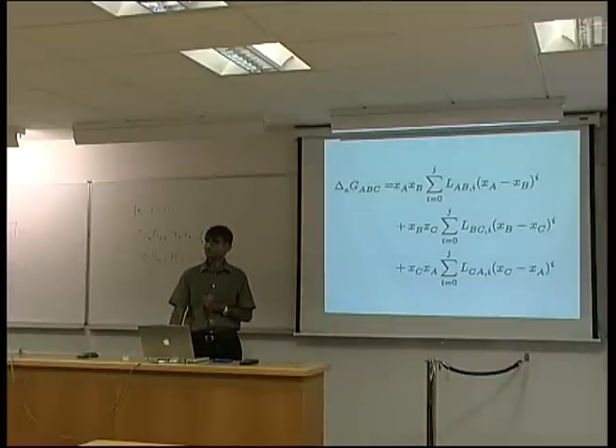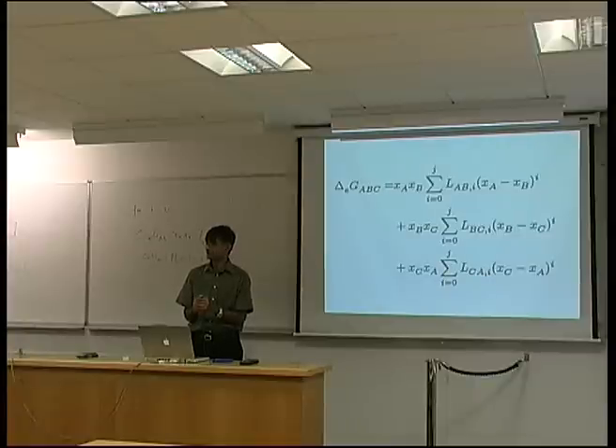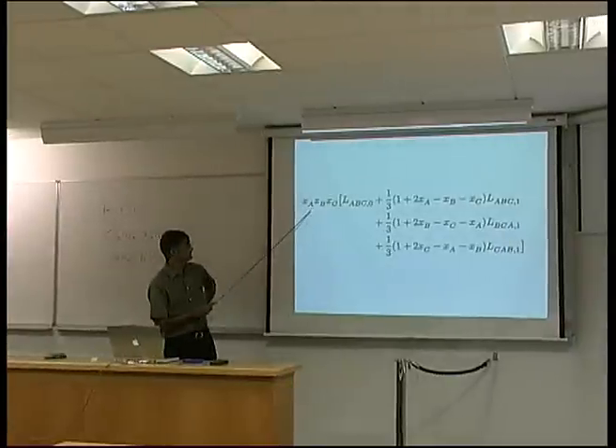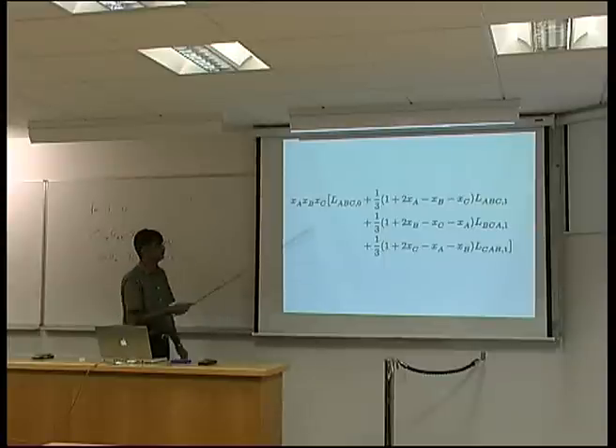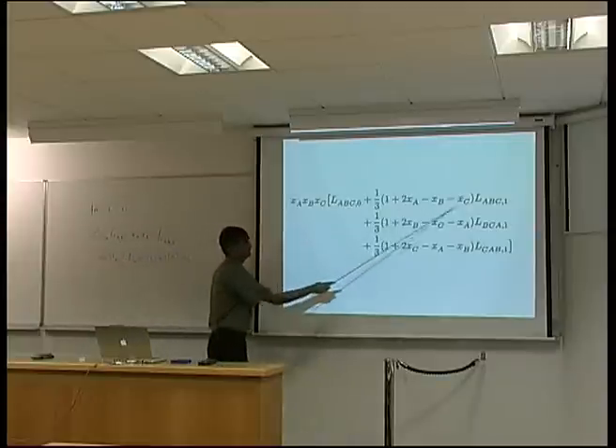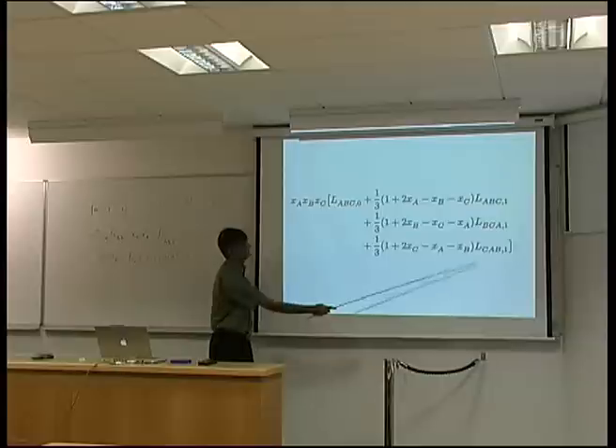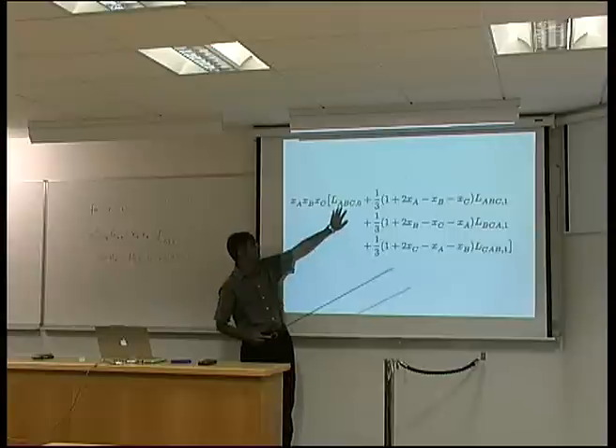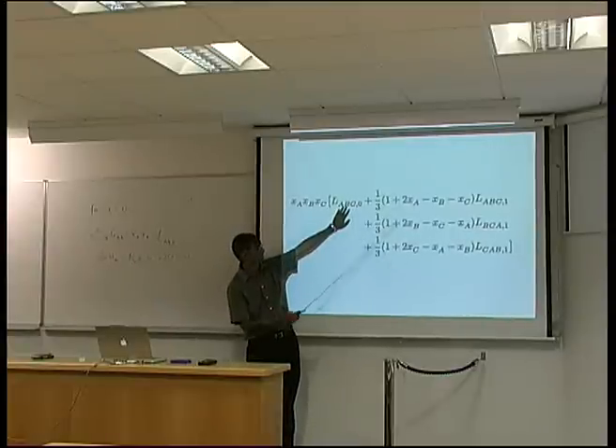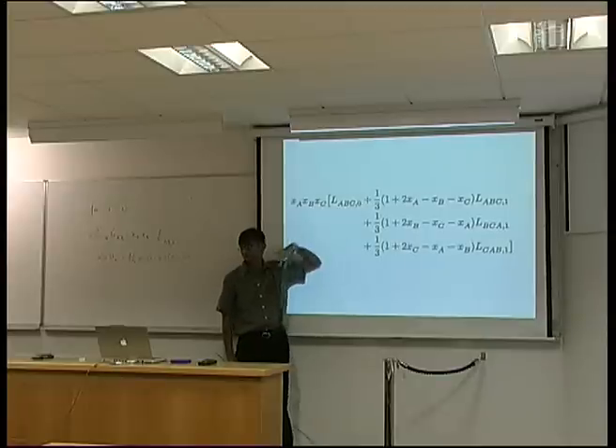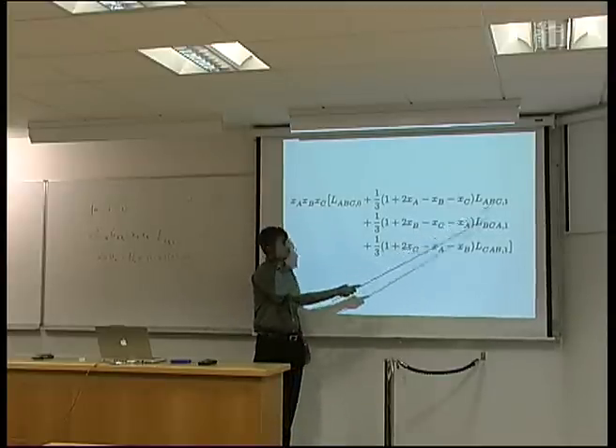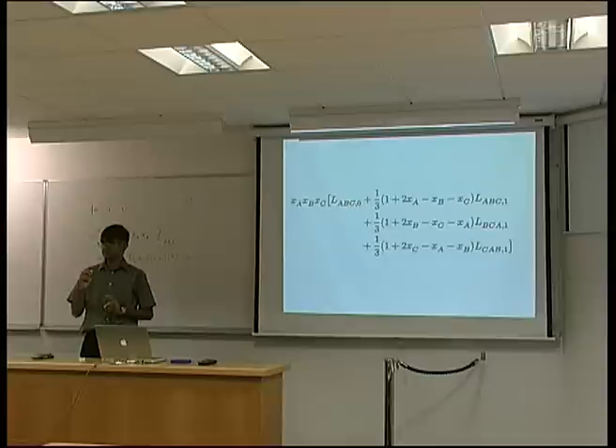So the way the equations are designed is that if you discover some inaccuracy or new data, you don't need to go back and modify everything else because the fit associated with A and B remains the same. But we are using an approximation here for doing a ternary calculation that there are no ternary interactions. We are simply extrapolating from the binary systems. OK, let's look at what happens if there really is a ternary interaction, if that is an important interaction.